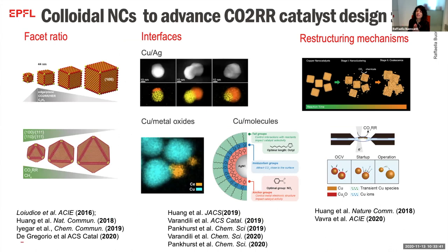So what I showed you with all these examples is really that we can start to use our nanocrystals to advance the catalyst design in CO2 reduction. So we understood that the facets that are exposed are important, but also the ratio between the facets is important. And we could do this only by changing the size. I also showed you that interfaces are important, so that just mixing the catalysts might not give you the fine tuning that is achievable by tuning the interfaces. And this is true for the different systems that I shared with you. And also that because they are so monodisperse in size and shape, they can help to elucidate the reconstruction mechanism. Now, I made the synthesis quite easy.